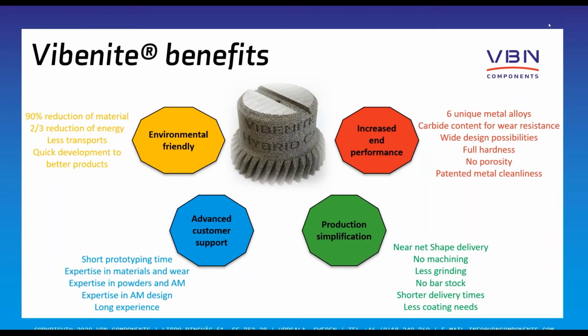The end performance is, of course, a very, very important part of this. And then we have the alloys, which I presented for you. But typically, we have very, very high wear resistance and very high hardness. And now you do not need to soft machine the materials. You only go for the final shaping, which is a form of grinding or EDM. You also have good possibilities to use the additive manufacturing design possibilities. You can have full hardness. The materials are also totally pore-free, so that you can get a very, very good material all the way through in some different applications.